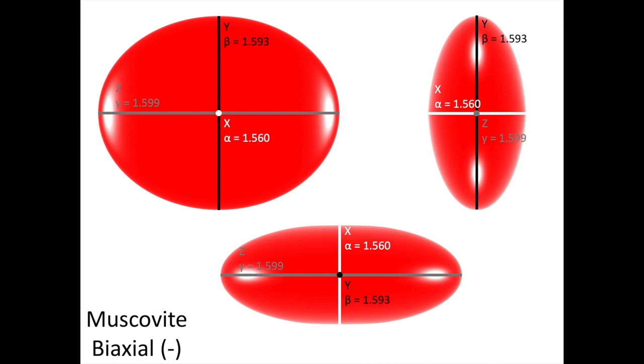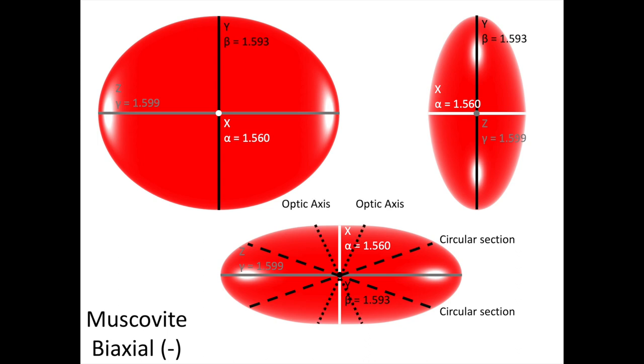Our muscovite is going to be biaxial negative, which means that refractive index beta is closer to refractive index gamma than it is to refractive index alpha. Our biaxial muscovite is going to have two optic axes perpendicular to circular sections through the optical indicatrix. And these circular sections have a radius of refractive index beta. The angle between our two optic axes is going to vary for muscovite between 30 and 47 degrees. This is in part due to the variability in the refractive indices of our muscovite.